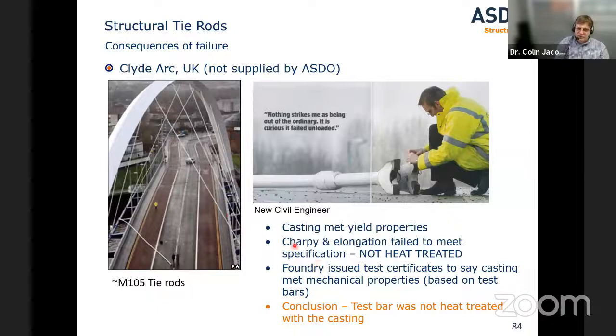What was found in the end was that the casting actually met the yield properties. So as you can imagine, they cut some samples from the casting. They found it met yield properties, but the Charpy and elongation, i.e. ductility, failed to meet specification. It's almost as though the casting had not been heat treated. Yet the foundry had issued test certificates to say the casting met mechanical properties because these were based on the test bars. And there was no control over whether the castings went through the same process as the test bars. So really the conclusion of this investigation was that the test bar was not heat treated with the casting. So whilst it maintained the strength after a few years of being loaded, it basically just failed in a brittle fracture.